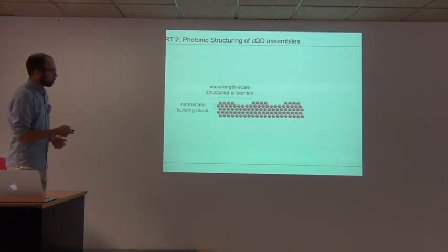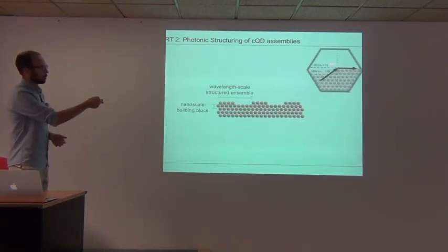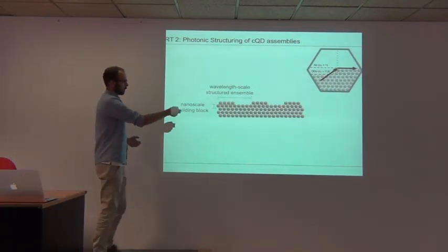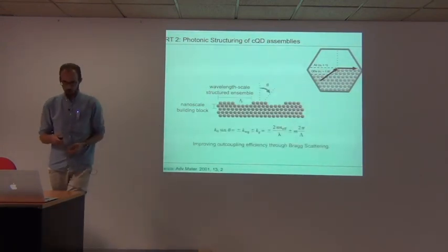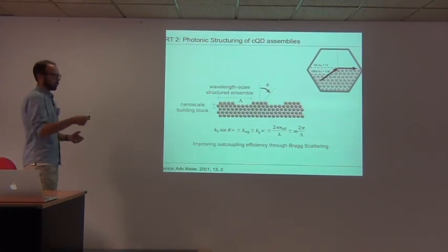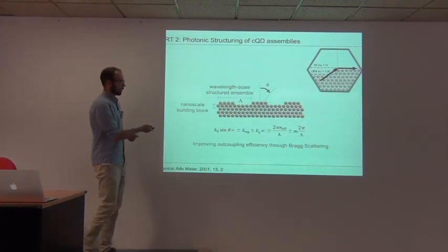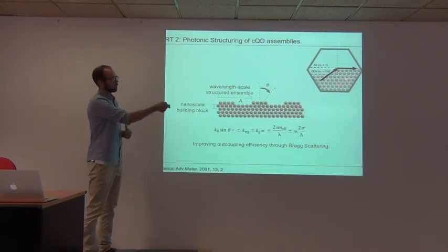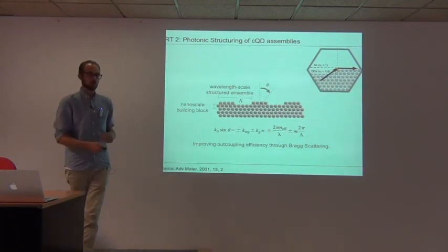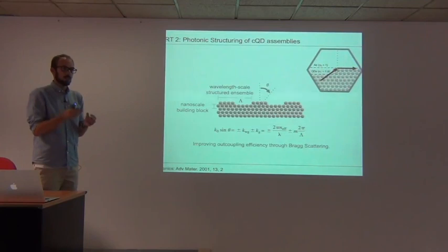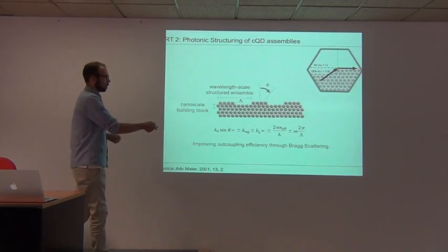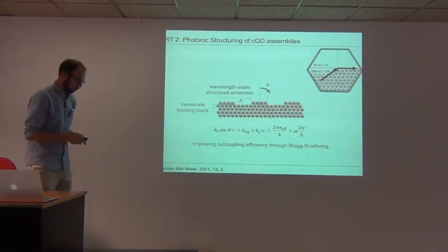So coming back to the original problem of the waveguide moding from two slides before, I'm drawing here a grating type structure, and this is not coincidental because, of course, in organic or solid state light emitting diodes, it is exactly these kinds of gratings that give you Bragg scattering that allows you to couple light out despite the difference in the refractive index, because the grating is giving you this additional momentum. So for a specific color of light, you can change the pitch to get a specific direction of outcoupling. This is just creating constructive interference.